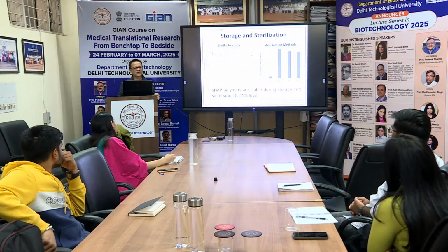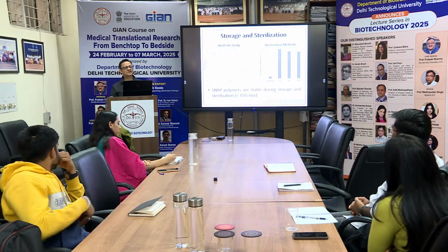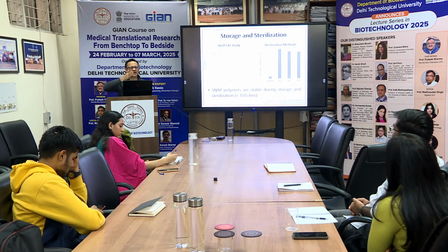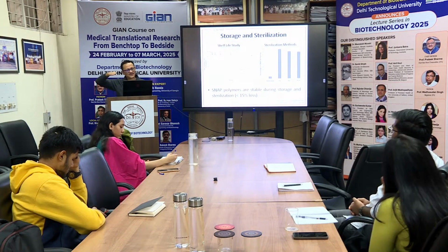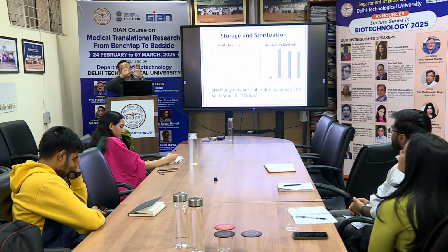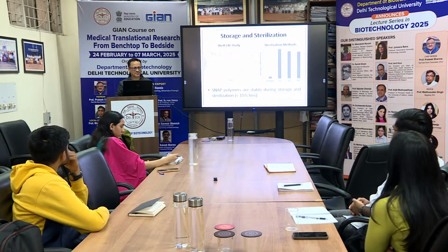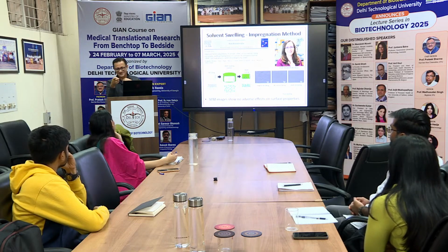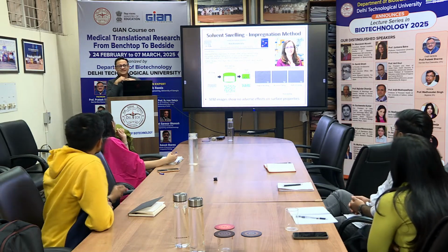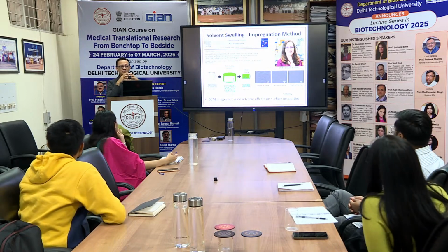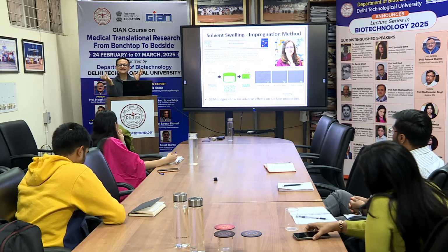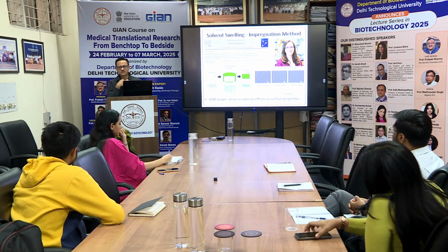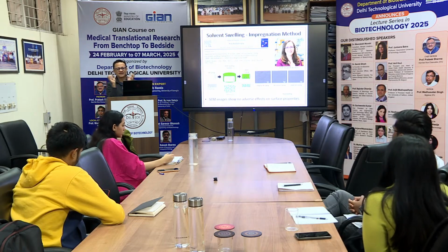Mostly for any NO release polymers we make, we see that with NO release also. A lot of times we see a little bit higher NO release on day 1 or 2, and then it starts going a little down because of that uncrystallized SNAP that's just sitting around there. It's actually good that it's very crystallized. Yes, preserving for longer. So that's why we were very happy when we got 20 days of NO release. That's stabilizing SNAP inside the polymer. Otherwise, the NO donor can just run out.